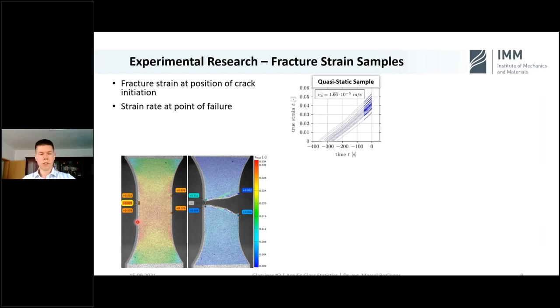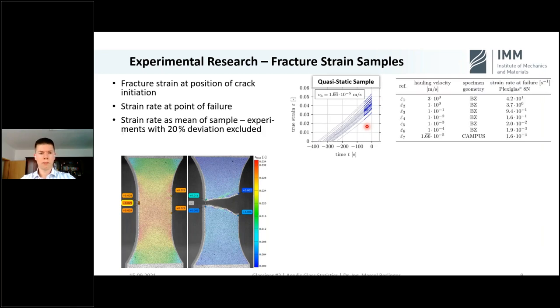Now, a second parameter, we took the strain rate. Here we have one sample of equal falling velocity. And you can see at the strain time curves, we took the slope and made a mean for the sample. So there is one value for one sample for the strain rate, but it showed that single experiments had too much deviation from the mean value. So we decided to cut experiments with 20% deviation from the mean value. And so in the end, we got 7 samples.